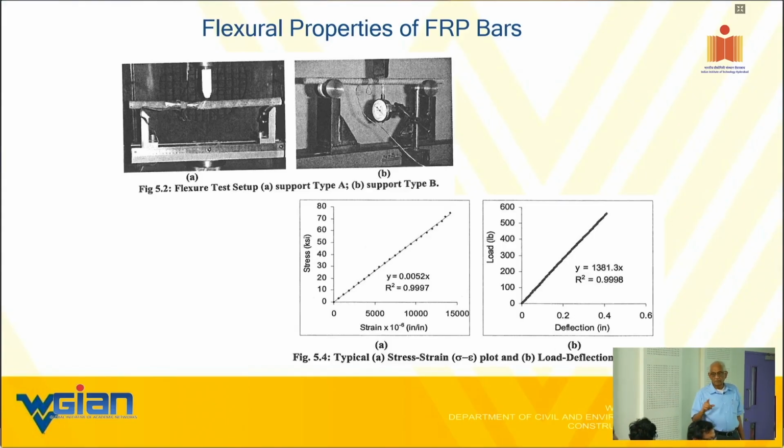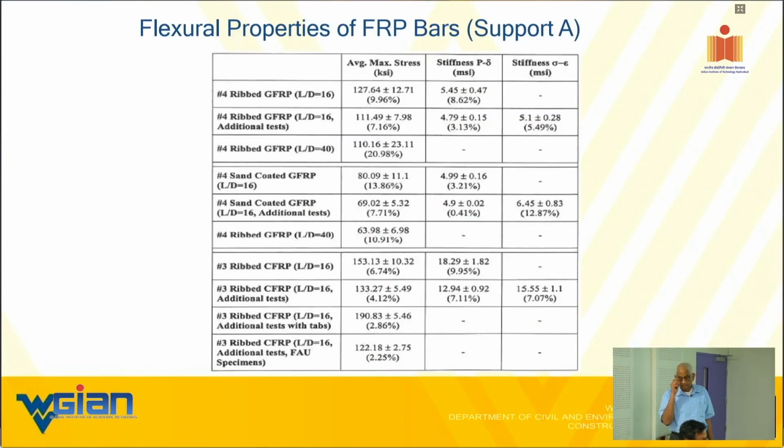Sir, in the latter slides, in various environmental zones, like the alkaline exposure and all, what was the binding material there, sir, for the FRP bar? Earlier we used polyester with polyurethane coating, right, that's earlier. Yes. But later on we have consistently used vinyl ester.